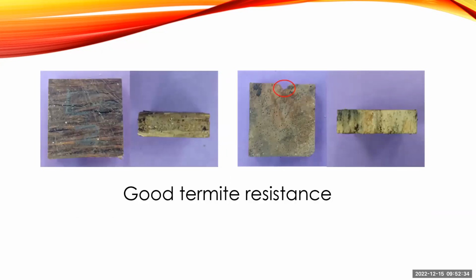The resin treated plywood also shows quite good termite resistance. We see no visible damage from termite attack, except some cracking, maybe due to the moisture in the jar.